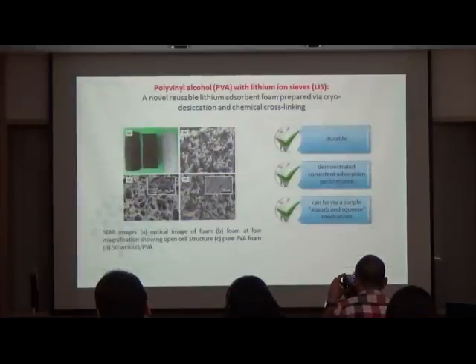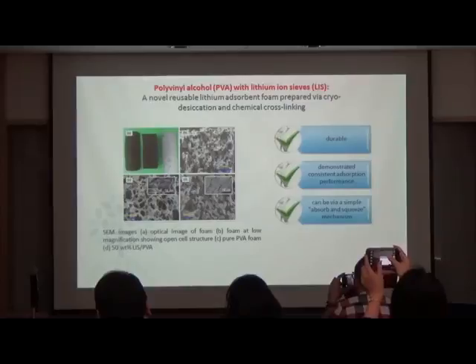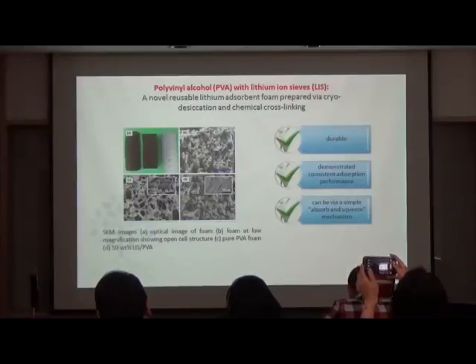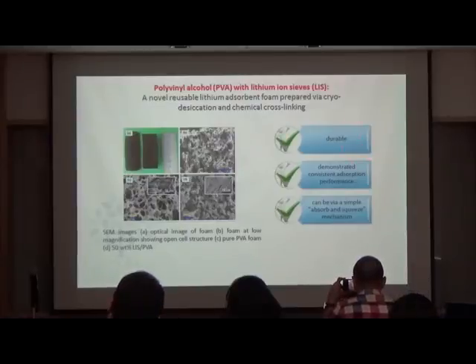In our study, the high LIS loading of the composite foam minimizes the effect of the PVA binder. Hence, our composite is remarkably better than those reported in previous literature. Our composites are hydrophilic, have high total porosity, and have high BET surface area. These properties contribute to the excellent performance of our materials. Furthermore, the composite is durable, it demonstrates consistent adsorption capacity, and it can be applied via an absorb and squeeze mechanism, which is far better than the energy-intensive packed bed and membrane system. So we can say that this study is better compared to those previously reported in literature.